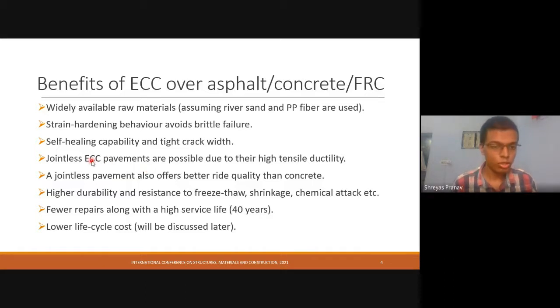And jointless pavements automatically means there will be very low material ingress and also a good riding quality for the vehicles. And in the literature, it has been proven that a typical ECC specimen has much higher durability and resistance to freeze-thaw, shrinkage, etc., than typical concrete. And because of these reasons, it requires comparatively fewer repairs. In fact, only minor repairs are required throughout the service life. No major rehabilitation is required over the entire service life, and it has been shown that it can go up to a minimum of 40 years without requiring much repair. Of course, then the most important aspect is the cost, which will be discussed later, and that is one of the objectives of the study.